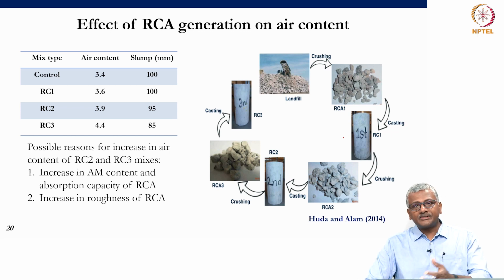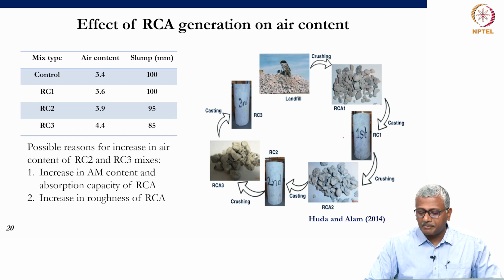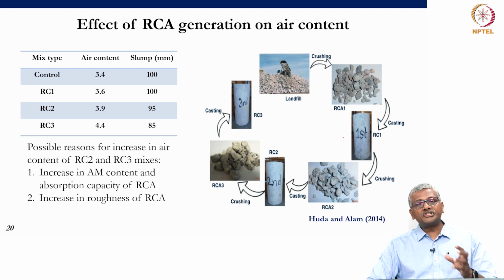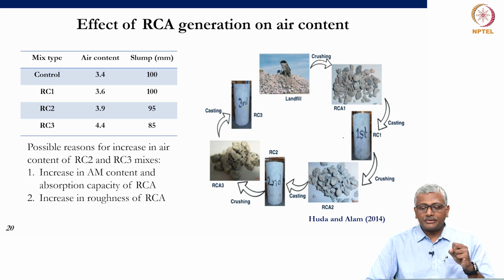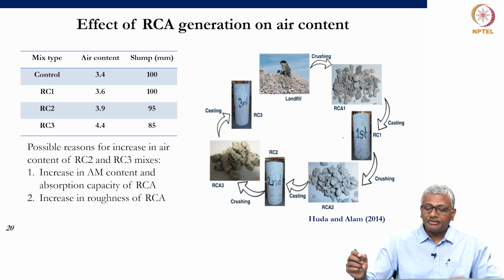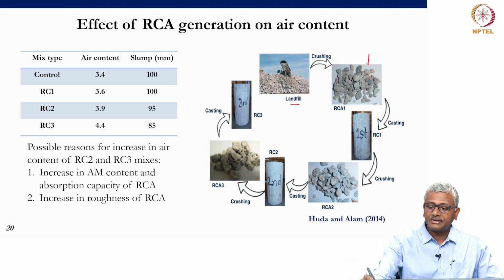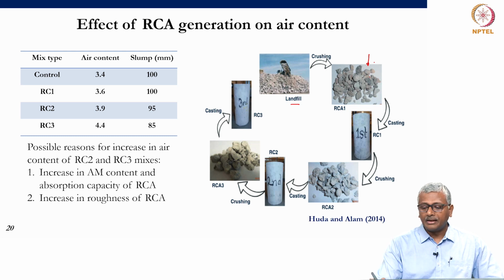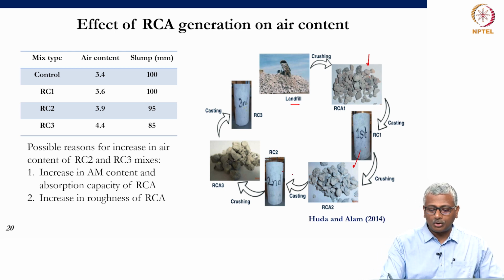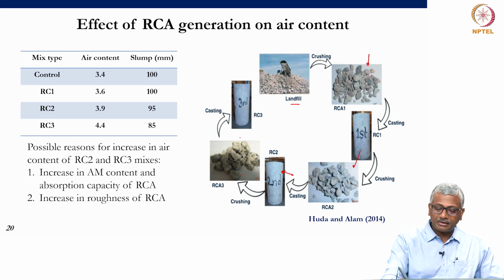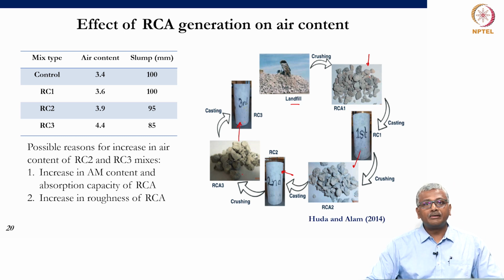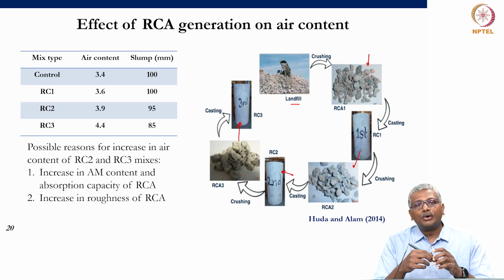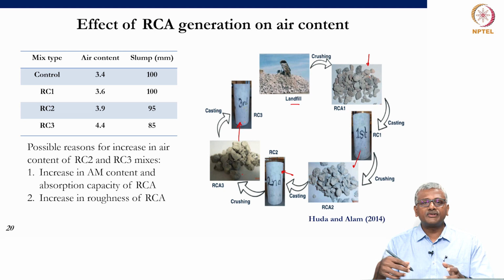Now, in some instances, for instance, this was a very interesting paper by Huda and Alam, where they have looked at the generation of the recycled aggregate. What do you mean by generation? So, they have from the landfill, they collect aggregates, which is the first generation recycled aggregate, and they prepare concrete with it. They then crush this concrete and prepare the second generation of recycled aggregate and prepare one more concrete with it. Then they crush that concrete and prepare one more recycled aggregate concrete with it. So, this is like 3 generations of recycled concrete aggregate.